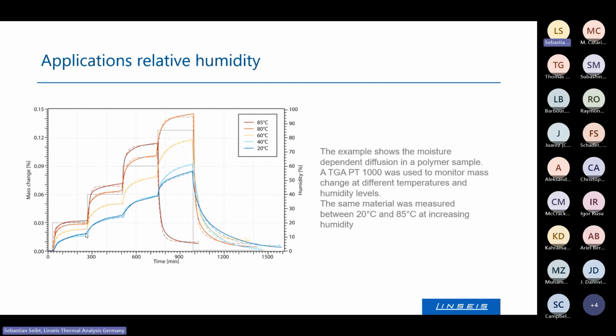And these curves are corrected, by the way. So there's a zero correction done without any humidity, and then without any sample at different humidity levels to make sure that this effect you see is coming from the sample and not from your setup and system.